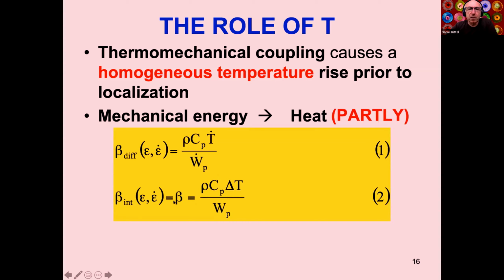Later work looked at this coefficient, but from the following point of view: a ratio of powers, thermal power to mechanical power, because it occurred to me that what you see in the coupled heat equation is this coefficient, what we call the differential coefficient, in which the coupled heat equation, the differential equation, is in fact invoking a ratio of mechanical powers and not mechanical energies. And then there's a sort of confusion in the literature, in which people are just considering one Taylor-Quinney factor and they're not referring to the differential.